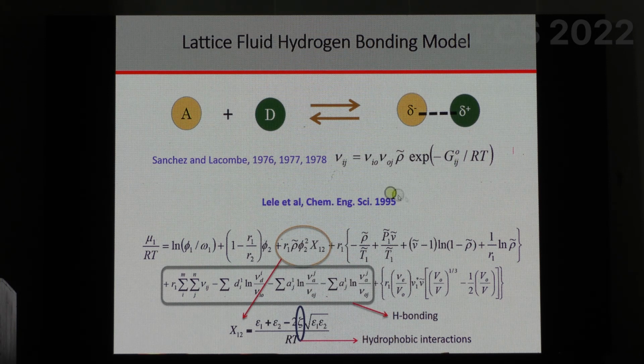And using these kinds of theories, you can actually expand the Flory-Huggins model and incorporate a term that accounts for hydrogen bonding, very specific hydrogen bonding between donor-acceptor groups, and a term that talks about interactions other than hydrogen bonding, dispersion interactions, which in a way talk about the hydrophobic interactions. So here is now a model that has the ability to capture both these interactions, the hydrogen bonding interactions and the hydrophobic interactions. And we need to add, of course, the elastic force terms to it.